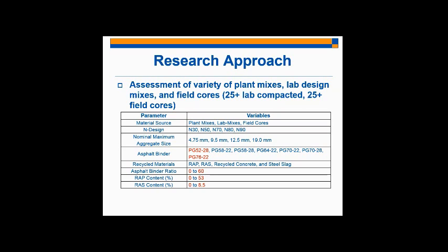And we've selected the mixtures used in this study strategically. We wanted as diverse a spectrum of properties as possible. You can see from this table that our asphalt binders range from PG 52-28 to PG 76-22. We have a nominal maximum aggregate size of 4.75 to 19 millimeters. We have N30 to N90 design values. We have all kinds of recycled content in our mixtures.